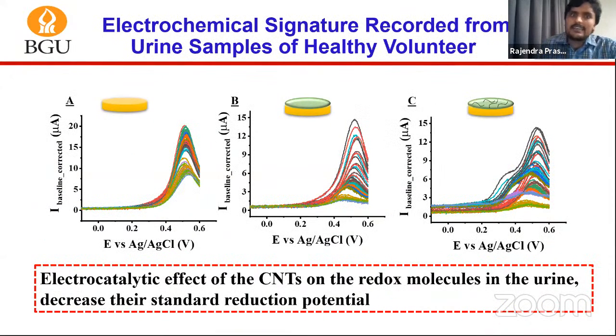Here on the screen, you see three kinds of electrodes. The first one is a bare microelectrode. The second one is a chitosan modified microelectrode, and the third one is a chitosan carbon nanotube modified microelectrode. This electrochemical data set is just for one repeat. We have many repeats, and you see here the different labels, the amplitude, and also the shift, and another peak appearing with the chitosan carbon nanotubes. Look at this high electrocatalytic activity that you can see.